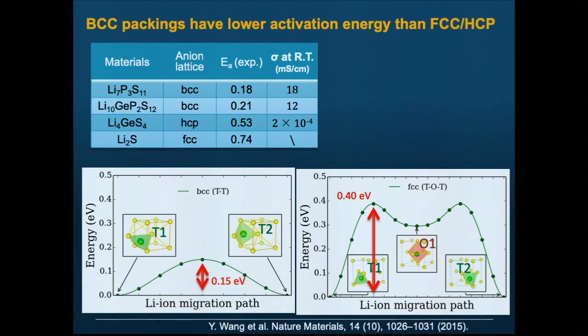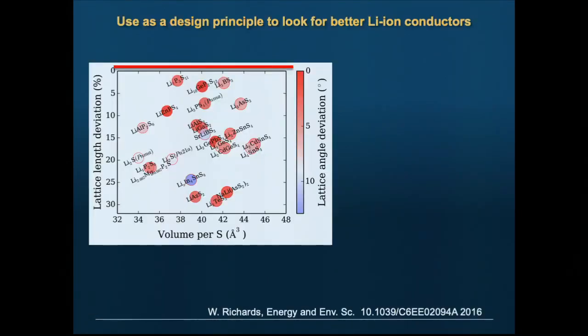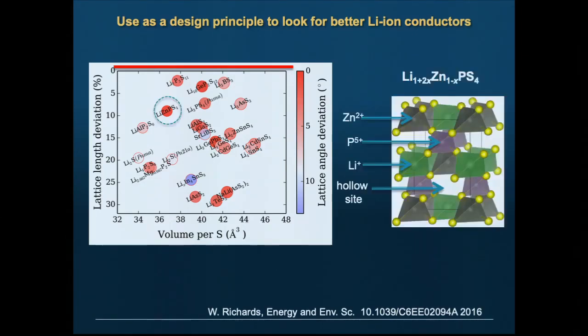There's nothing else around. And indeed, if you look at some really good conductors like LPS and LGPS, they have BCC anion backbones. If you just take everything else away, the anions show a BCC structure. Whereas if you look at some worse conductors, they have HCP or FCC backbones. So this was a key insight, because now you go, I'm just going to look for more compounds with BCC backbones, right? And so you search through the ICSD, you code up a few algorithms to look for how the anions are packed, and we found one that nobody ever thought about, a lithium zinc thiophosphate, or LZPS as we call it. It has a BCC backbone.